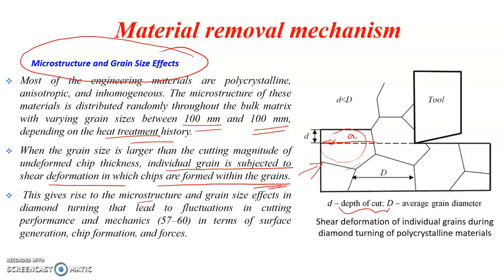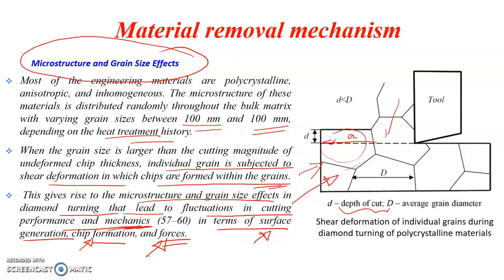which gives rise to microstructure and grain size effects in diamond turning that lead to fluctuations in cutting performance and mechanics in terms of surface generation, chip formation, and forces. So the surface to be generated, that is the surface finish, and the chip formation, whether it is a continuous chip or an intermediate chip, and the cutting forces, everything depends on the nature and the size of the grains. So with respect to the type of grains, it may differ. So grain to grain or material to material, we need to provide different cutting parameters.